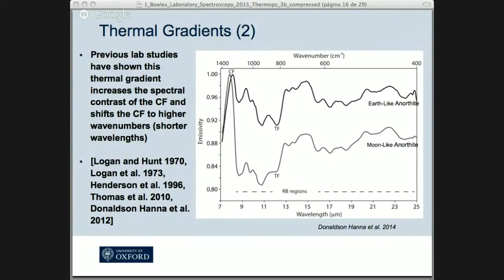So you get this big thermal gradient when you move from Earth-like to Moon-like conditions, and you get this shift in the diagnostic feature peak, the silicate diagnostic feature, the Christiansen feature, and then this big change in the spectral contrast. Now, the important thing to notice here is that this is a pure mineral sample. So this is going to have a fairly uniform set of optical constants. There's no real mixtures going on. So that's why we see these big changes.